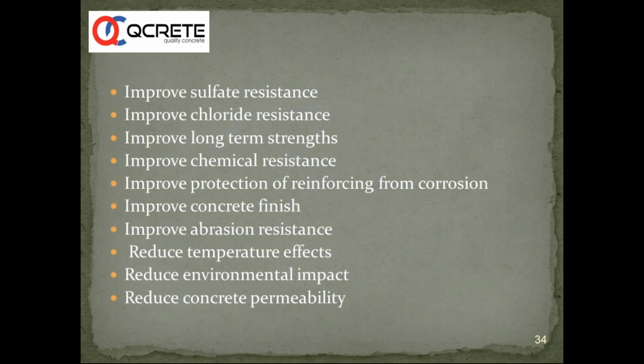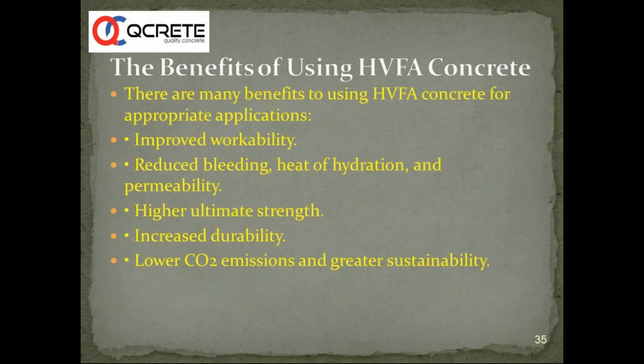We also have not only smaller amounts of fly ash, there are concretes made with high amounts of fly ash, which is also called as high volume fly ash concrete. Many benefits are there when you are using high volume fly ash concrete. It has improved workability, reduced bleeding, heat of hydration is reduced, permeability is reduced, higher ultimate strengths, increased durability, lower carbon dioxide emissions, which we already talked about, and very good sustainability. So high volume fly ash concrete has already been there.